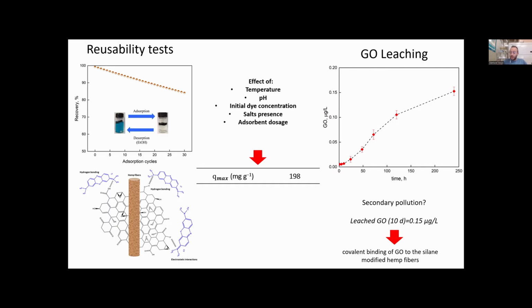And you can observe that after 240 hours of continuous use of graphene oxide modified hemp fibers, the leaching concentration is about 0.15 micrograms per liter, which is below the threshold established by the European Community for this compound. And this can be mainly ascribed to the covalent binding, as discussed previously from FTIR data, of graphene oxide to the silane modified hemp fibers, which is supposed to occur between the amine group of the organosilane and the carboxylic and epoxy groups of graphene oxide.